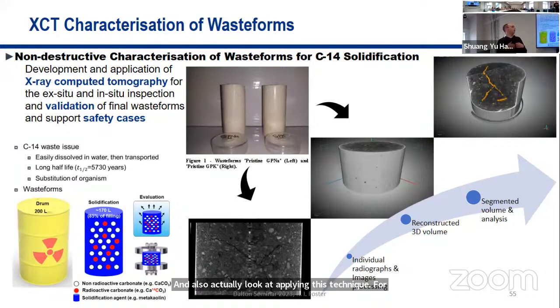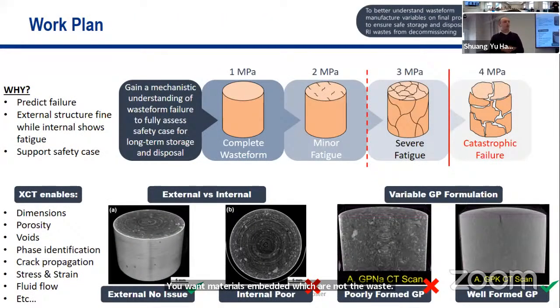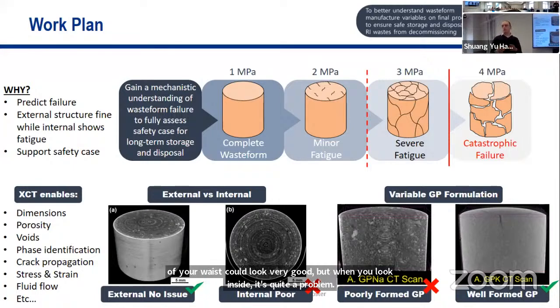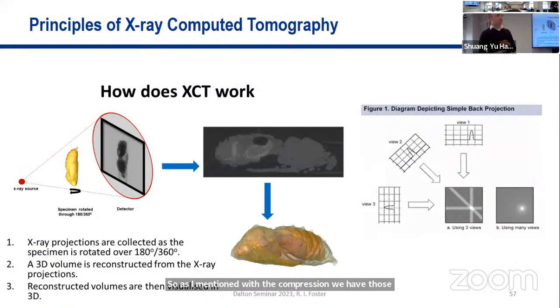There's no way of knowing. The outside of the waste form might look great, you've formed it very well, but actually internally you've got things like flash setting, where, as this one shows, you've got materials embedded which are not the waste, it's actually the matrix of the waste form, which causes issues for long-term disposal. So essentially, the outside of your waste could look very good, but when you look inside, it's quite a problem. As I mentioned with the compression, we have those issues there. So that's why we're going to look at X-ray computed tomography.